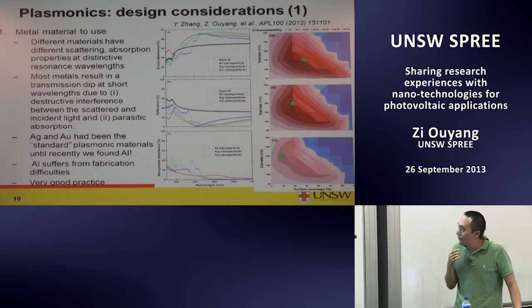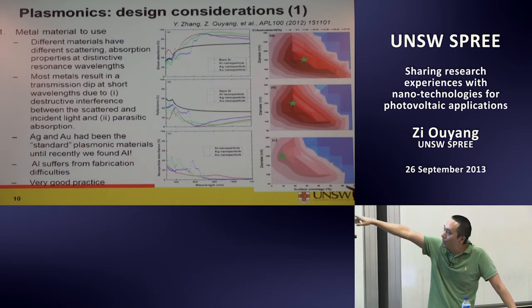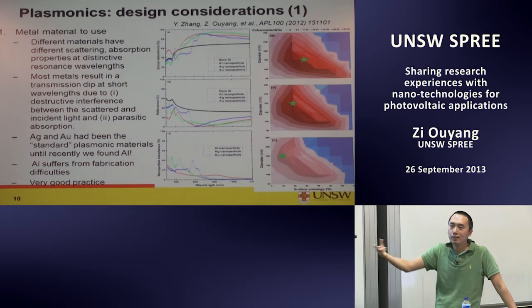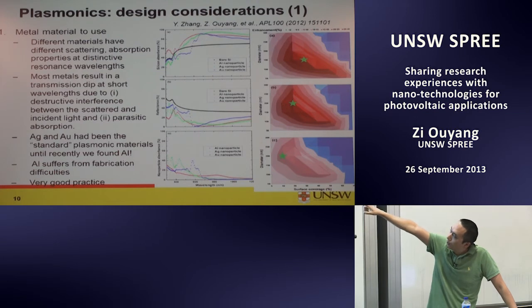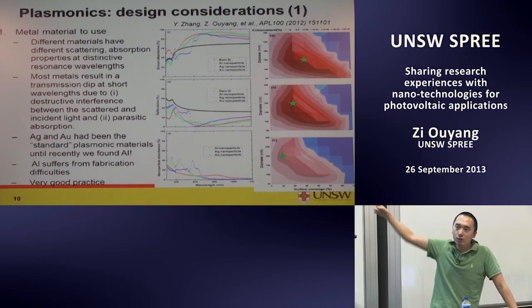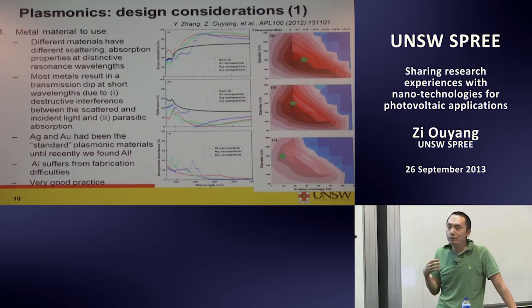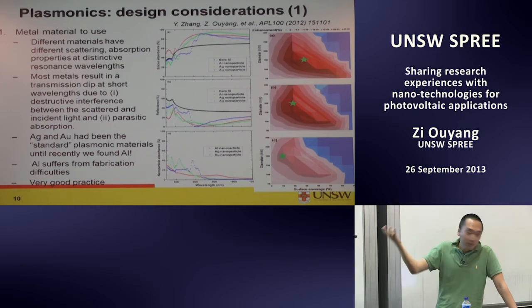For most of the particles, you see you have significant absorption here. That's because basically the oscillation in the particles just becomes heat. And for the other part, you also have a little bit of reflectance. That's because there is destructive interference between the incident light and the scattered light. That's what we call the Fano effect. So you see all the particle materials behave differently.